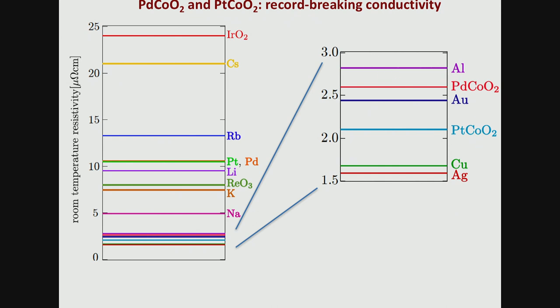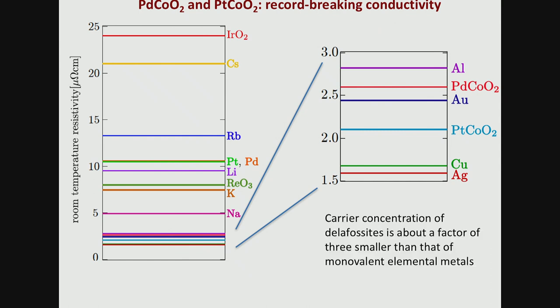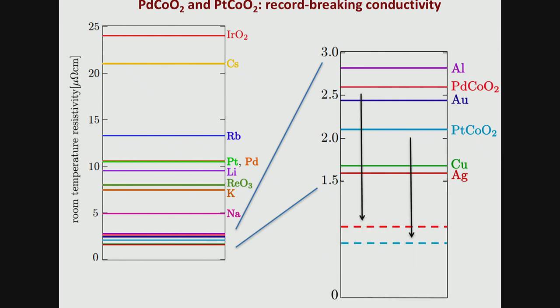What's even more surprising is that the way you relate resistivity to the microscopic mean free path always depends on the carrier density. The carrier density is much lower per volume in these materials because they're layered. So actually, the volume carrier density is about a third lower than it is in copper or silver. So in fact, of the proper metals, with one conduction electron per atom, that we know of, the delafossites are the highest conductivity at room temperature per carrier, which is not fully understood. We're working on it, but it was a remarkable fact straight away. I was aware that other people were working on these materials, only a few, and I thought, okay, we should be interested in these.